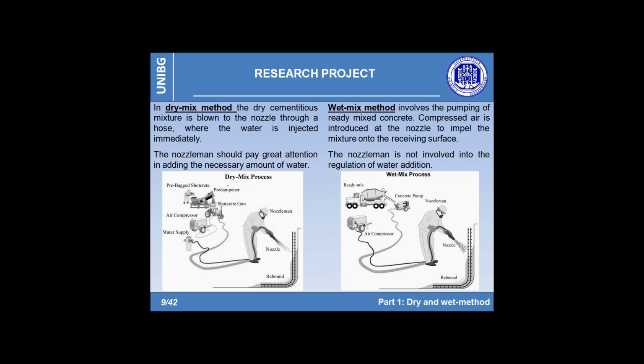On the contrary, in the dry mix method, the cementitious mixture is blown through a hose to the nozzle, where the operator should add water. It results that the nozzleman should be very careful in choosing the right amount of water, avoiding compromising the mechanical characteristics of the final product.